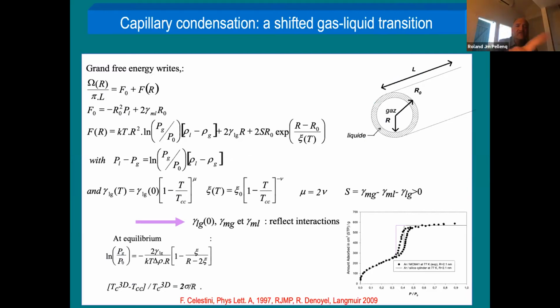It's just my point that you can write down this free energy of a fluid layer in equilibrium with the gas phase. Very simple. You have a surface term and a volume term coupled through this exponential term. If you write down the FR, the free energy of the system, that's the exponential term. Then when you go down through everything, you can derive the Kelvin equation, the equilibrium relation you see at the bottom, with a term here that is the correction of the Kelvin equation when you go down to very nanoporous systems.